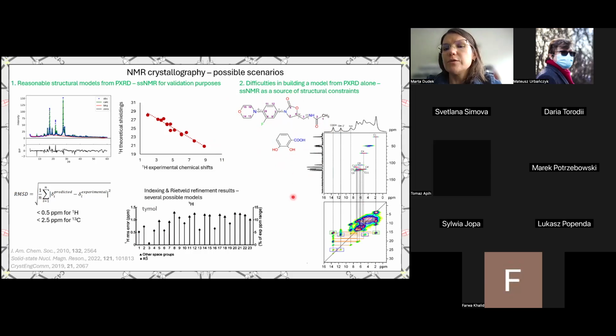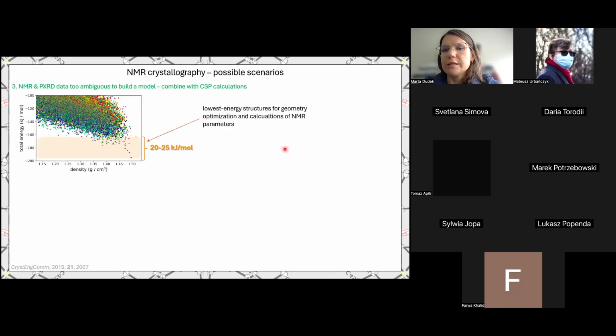To do that, you really need to pay special attention to all the details in the NMR spectra. In this case, we were able to determine the conformation of linezolid inside this crystal because of the interactions that we saw in the 2D spectra. We saw that this C6 carbon is in close proximity to this H12 proton. We also were able to determine the conformation of this molecule because of the hydrogen atoms that can be pointing in different directions. It can be really challenging. And then this model was used in further studies and refined against the experiment.